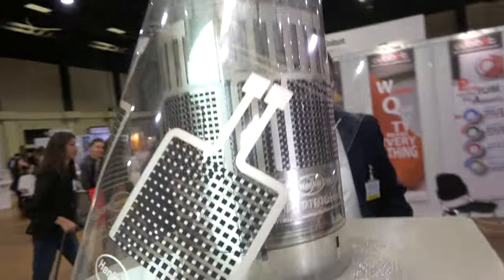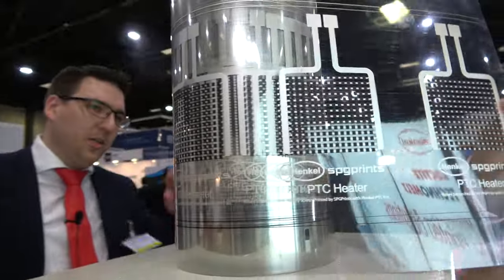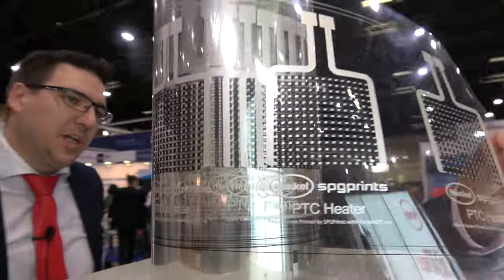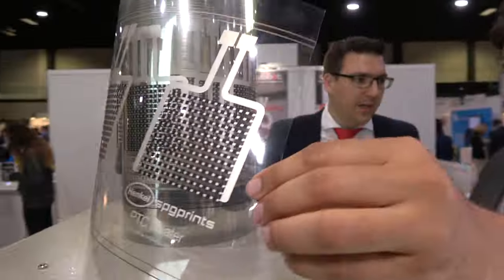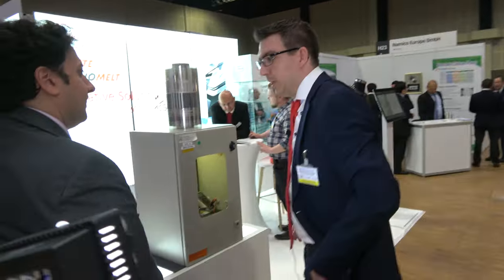We are a part of the adhesive business, which is concentrating on electronics. And within electronics, we have printed inks, which are either silver inks, carbon inks, or dielectrics. These are printed heaters which have a silver bus bar with a line-track silver with a PTC carbon ink printed on top, which has the functionality that it will go up to a certain temperature and then stabilizes — it has a positive temperature coefficient.